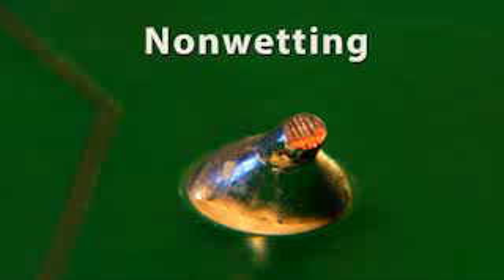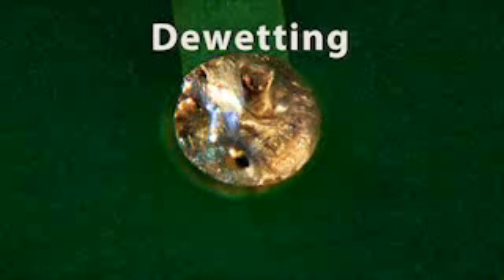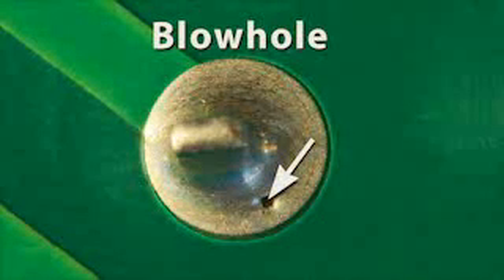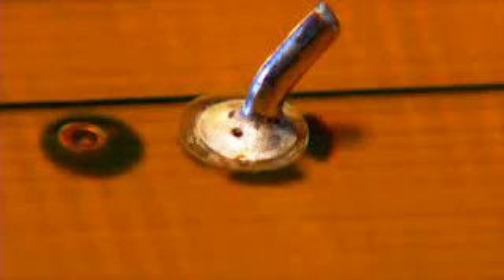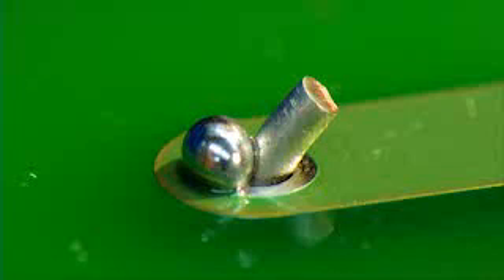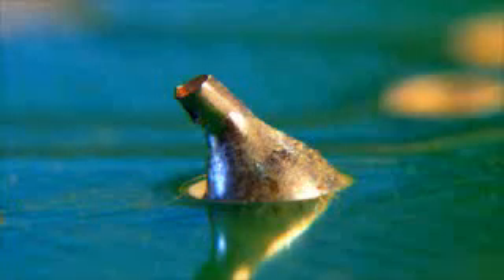Here's an example of non-wetting. The solder does not feather to a thin edge, and some of the base metal is partially exposed. Here's an example of de-wetting. Notice that all of the base metal is covered with solder, but there is an uneven fillet. The solder has receded in some places, leaving uneven mounds of solder. Another type of imperfection is the blowhole. These are usually caused by a gas escaping through the solder as it solidifies. If there is any moisture or solvent inside the hole or excess flux, this can create a blowhole as the gas expands and escapes.